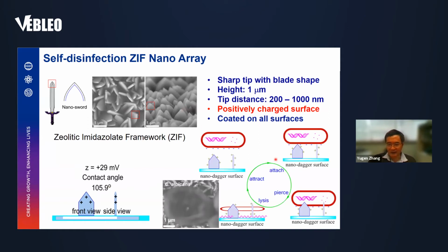And here is the killing mechanism for this type of structure. Basically, they have these sharp nanostructures, and they have positive charge. They attract the negatively charged cell membrane onto the surface, and then the sharp tips penetrate the cell membrane, causing cell lysis and cell death. Showing here is the SEM image. You can see these are C. albicans cells. Actually, they are really penetrated by the tips of the nano daggers.